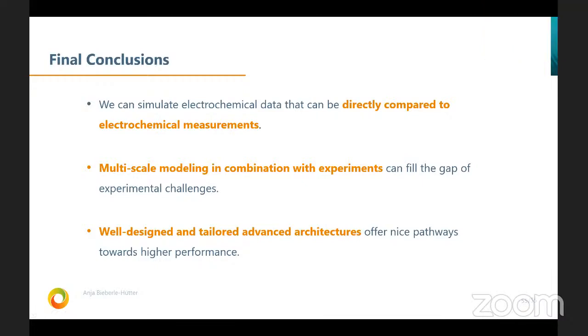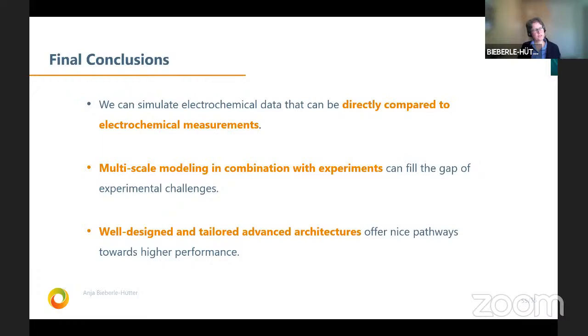Yeah. I am in the Institute of Catalysis and Petrochemistry in Madrid. And Anja, how did you explain that in the tungsten trioxide case, infrared irradiation gives nearly no response, while UV plus IR gives significantly higher anodic current than UV alone? You refer to these measurements when we separated UV irradiation and infrared, because the tungsten oxide is not active in the entire wavelength range, and this is the reason.